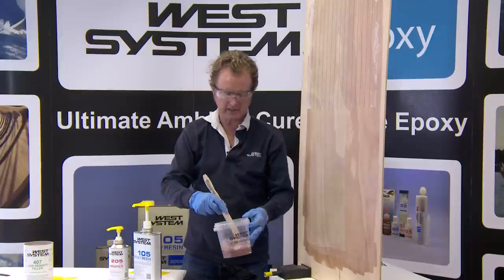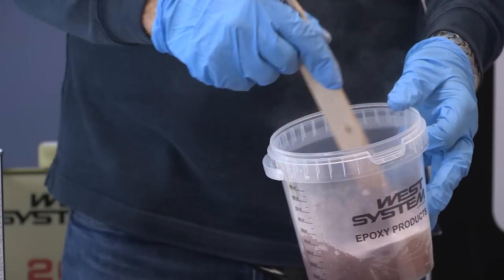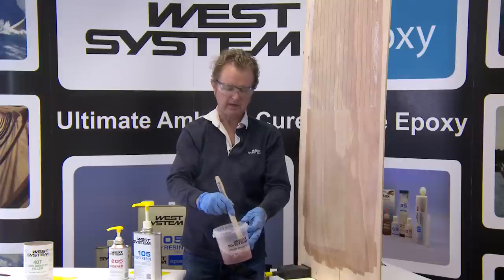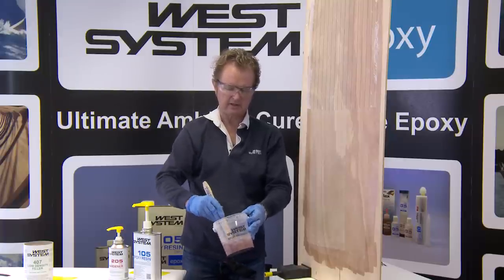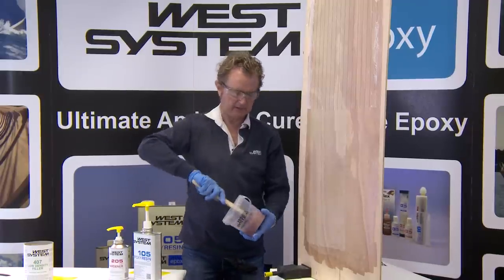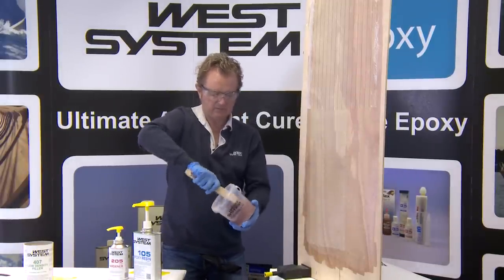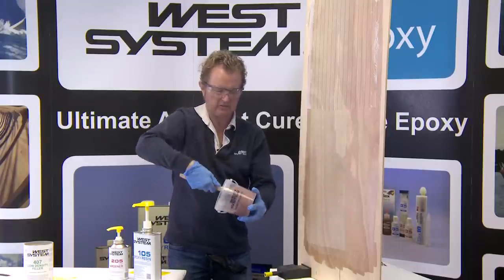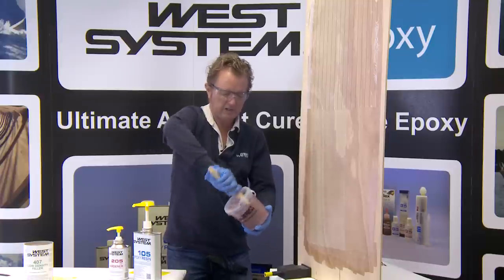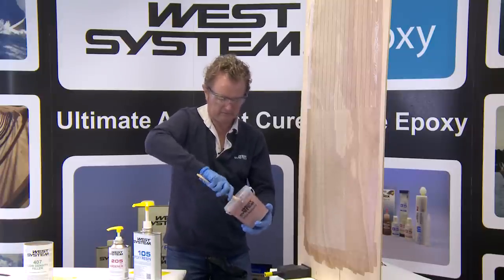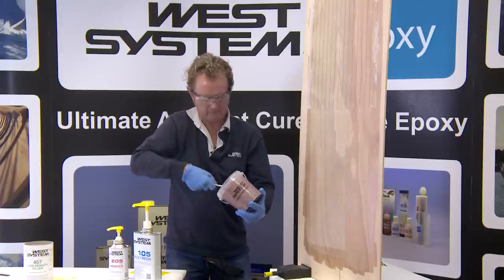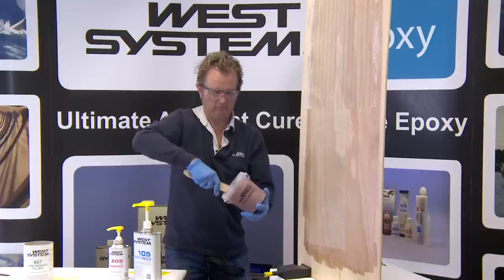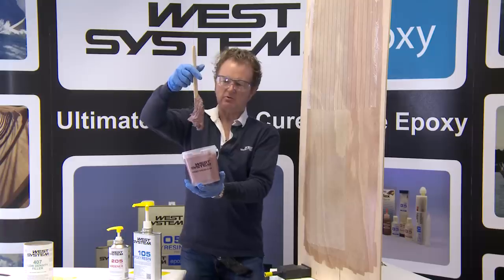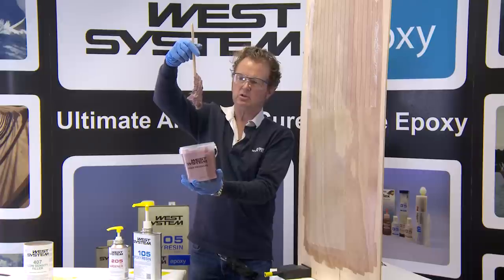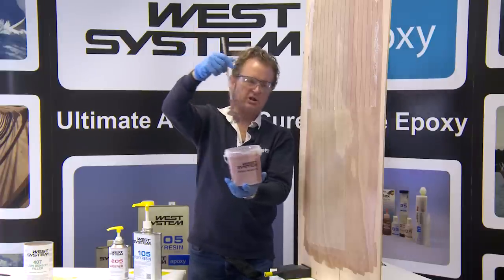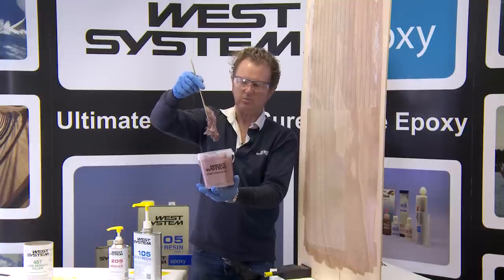Now this will take quite a bit of blending together. It's a good idea to carefully blend the filler with the epoxy. And very suddenly, you feel the two start to blend together. And you end up with a nice mix that you can really work on and get nice and smooth. This is why you need a sturdy mixing stick to do this. Spend some time blending the two together. And the real clue to the right consistency is whether this mix will be stable on your vertical mixing stick. Now, this isn't slumping, so consequently, this won't slump on the work, and that's exactly what we want.